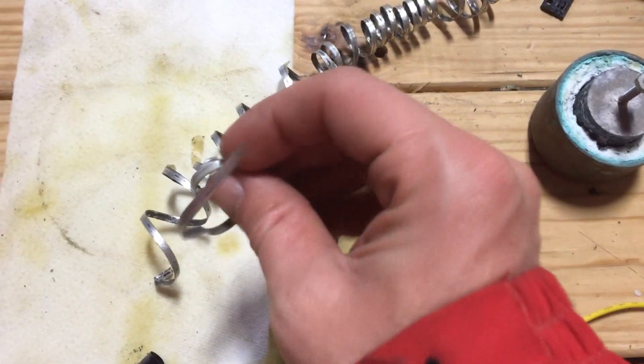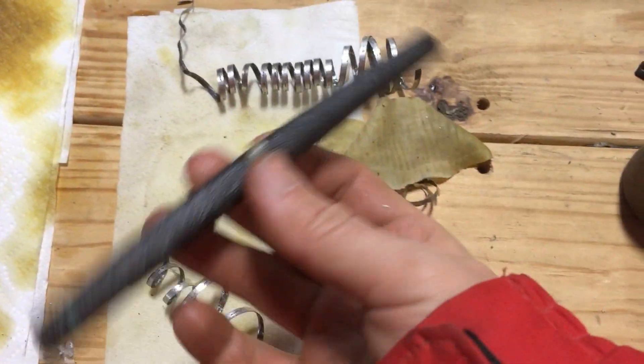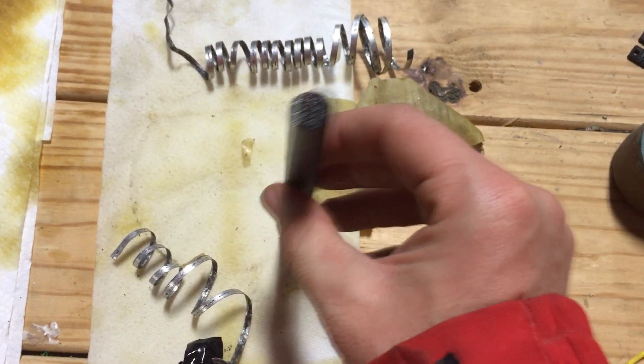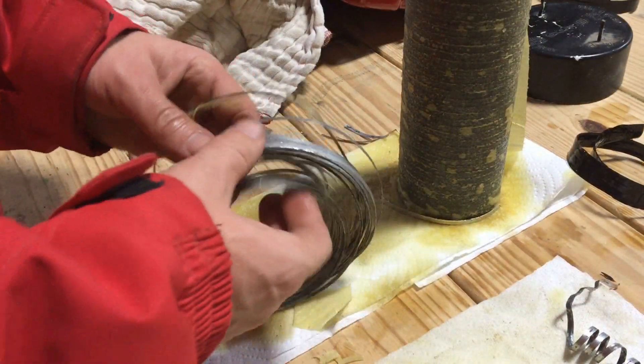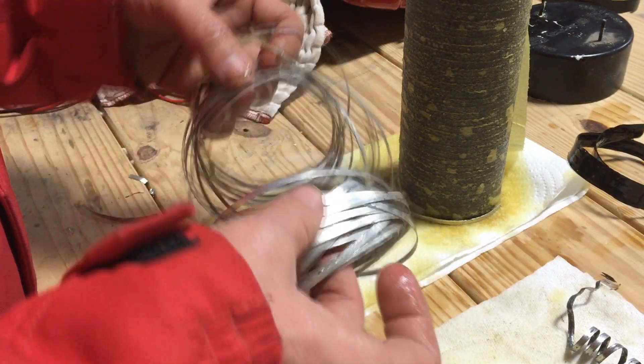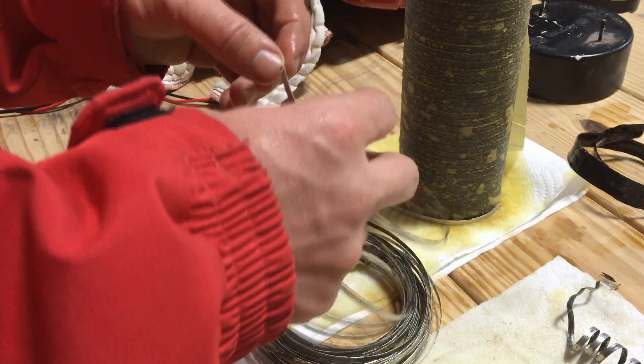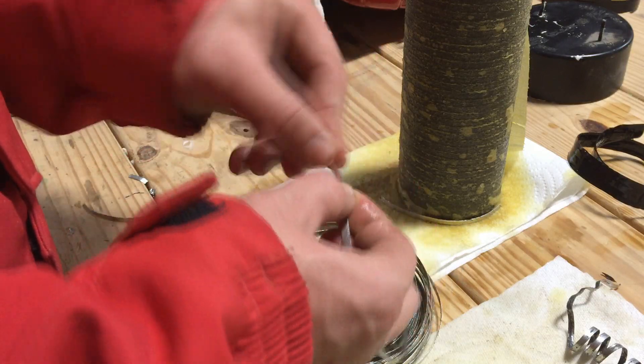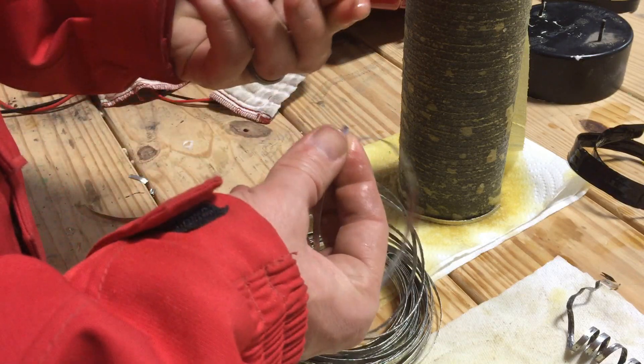I've got the ribbon off and did some bend testing and breaking on it — it's actually in really good shape, surprisingly good shape. All the magnesium ribbon came off in one piece. This is pretty much almost like a brand new roll of magnesium ribbon; it has a little bit of pitting here and there but it's in surprisingly good shape. I'll show you a break test: one, two, three, four, five, six, seven, eight, nine, ten — ten flexes to break it. It's obviously not pitted down through the structure of the magnesium and overall is in really good shape.